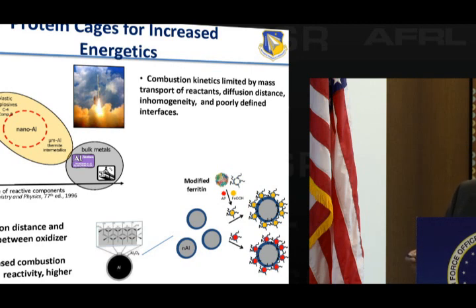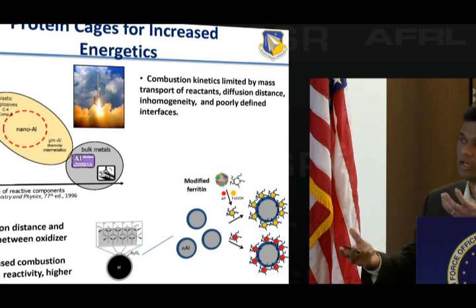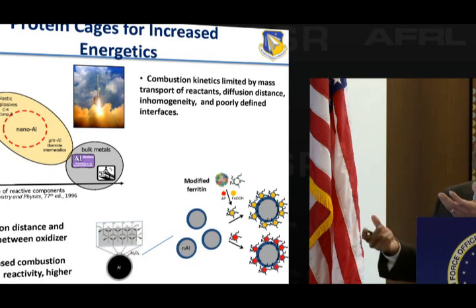Just because of time, I'm showing you that nanoaluminum is the material that we chose to look at because that's used as a material for combustion and maybe as a fuel in rocket fuel and other propellants. And the thing that limits a lot of these materials is that the combustion kinetics is limited by mass transport of the reactants, diffusion distance, and inhomogeneous mixtures. Because what people do is they take nanoaluminum, they either throw in an oxidizer, it could be using a thermite-based reaction, so you throw in iron oxide, or you use a chemical combustion process using ammonium perchlorate, you throw that in. But what happens is that because of poorly defined interfaces and the inhomogeneity of the mixture, you don't see an increase in the combustion kinetics.